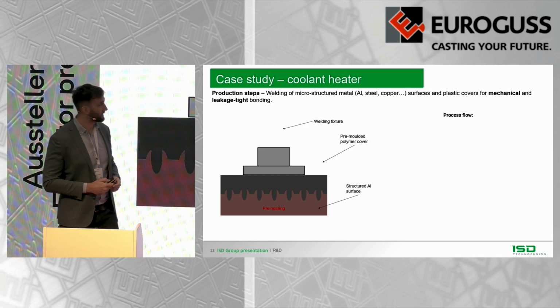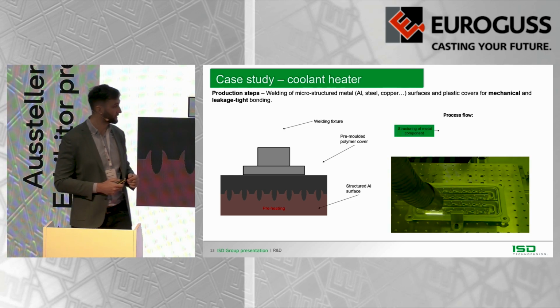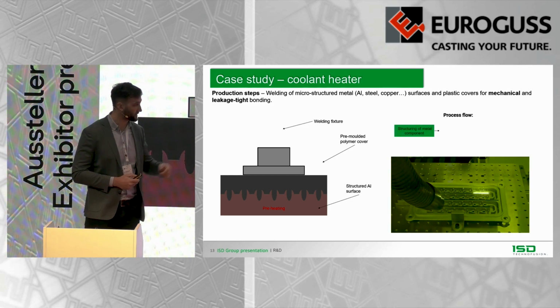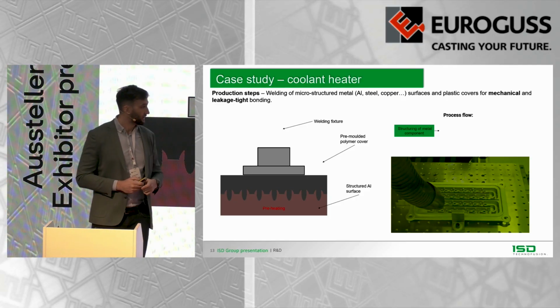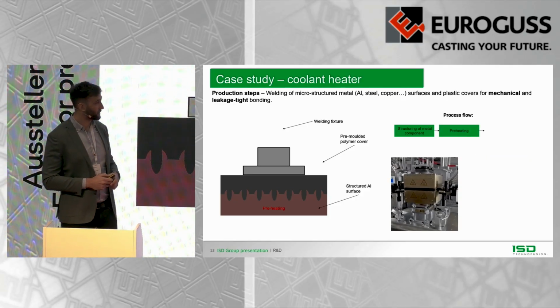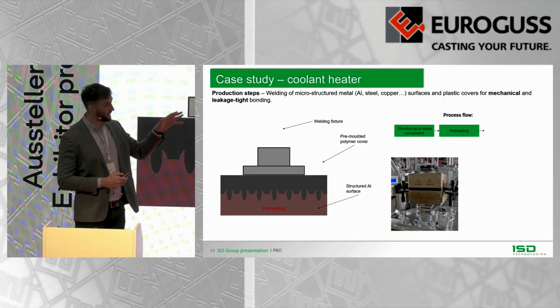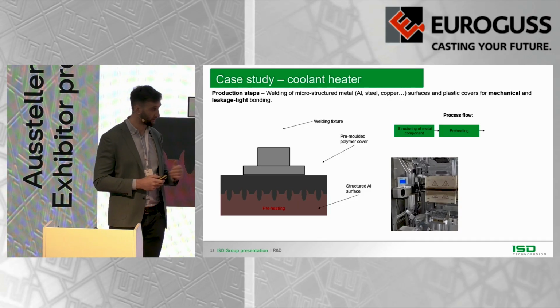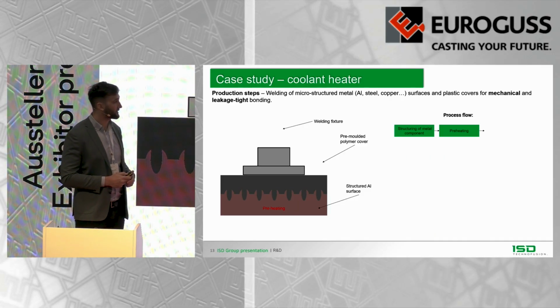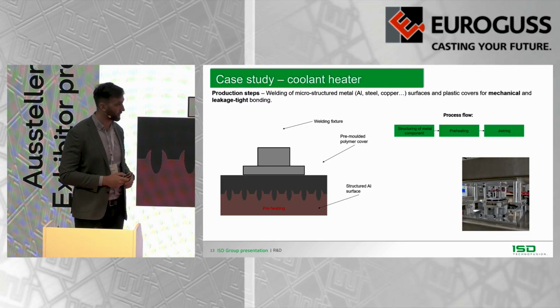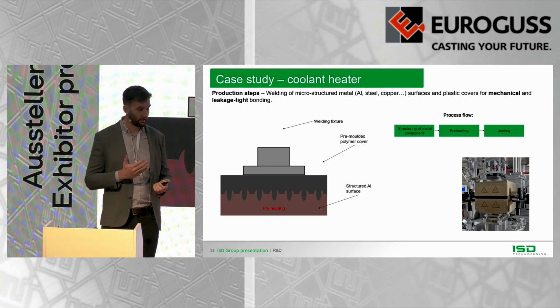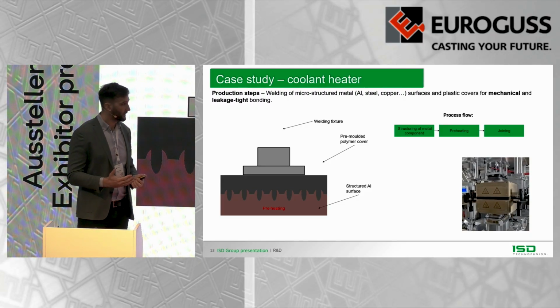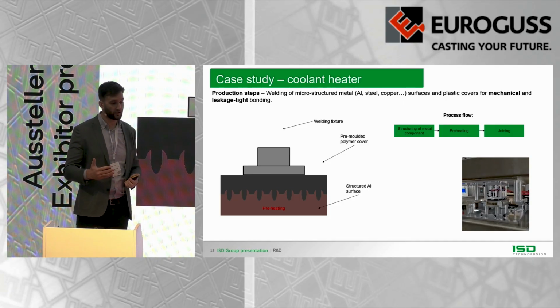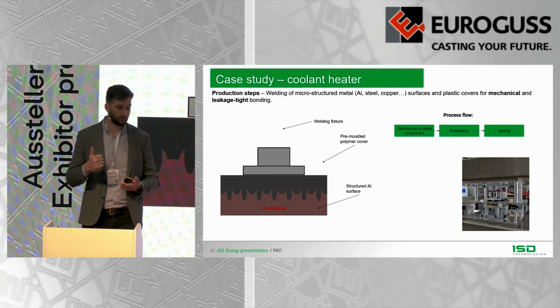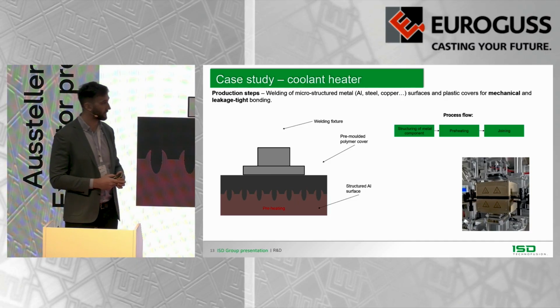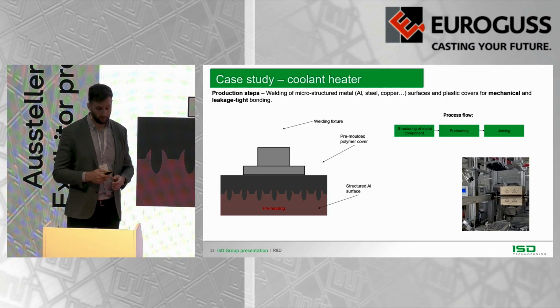Also to show you the process flow, it's a very short one. So here we have the part. We do first the structuring process. Then in the next stage, we preheat the welding area. And then after the preheating, the heating head is removed, and the parts are permanently joined together. So as you can see, it's a very short, simple process that removes several additional steps that you would normally find with either friction stir welding or perhaps laser welding or a standard assembly process.